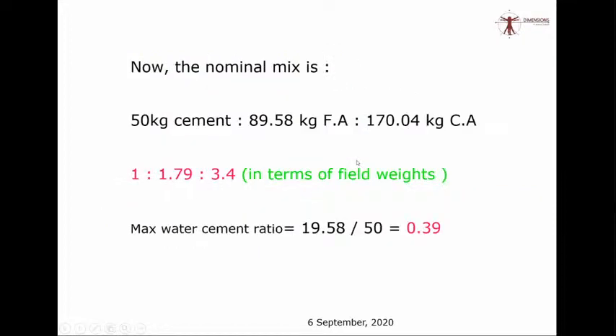Therefore, you will have to reduce the 10.42 kg from your 30 kg, which is allowed. So your maximum moisture content, water cement ratio will become 19.58, which is a result of 30 minus 10.42 divided by 50. 50 is nothing but the quantity of cement you are using. So water by cement, your water cement ratio is now 0.39. So 1 is to 1.79 is to 3.4 with a water cement ratio of 0.39 will be your actual nominal